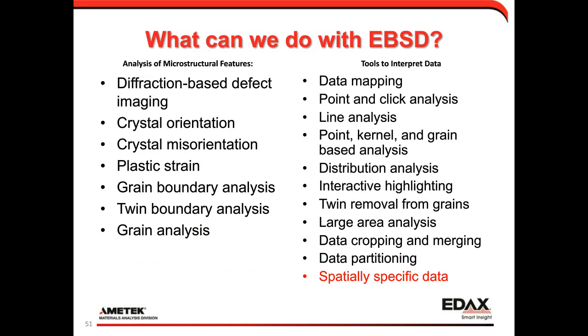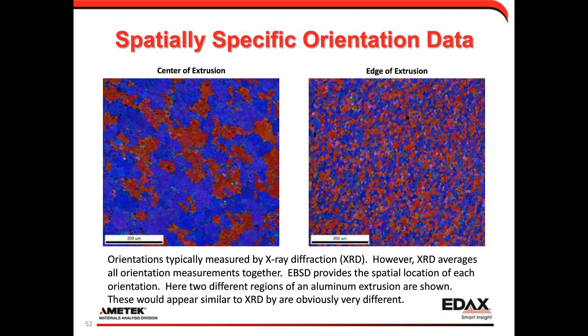One advantage of EBSD is we get spatially specific data. If we compare measurements with XRD, which will measure some of the same information from an area, what we lose is that spatially specific data, and we gain that with EBSD. And the reason that's important is that the spatial distribution of these measurements can influence performance.